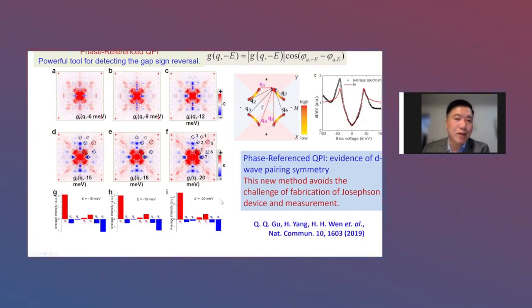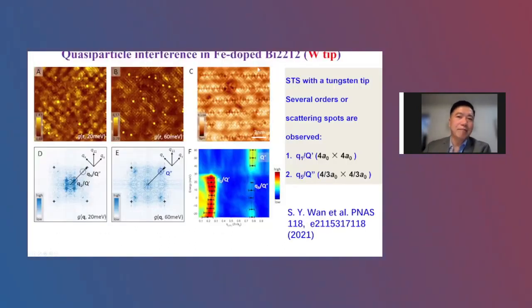Okay, so this is another story. Let me come back to the iron doped BSCCO 2212. So you can see that this is using tungsten tip measured density of states mapping. You can see this kind of block again. And when we do the Fourier transform, we see two sets of spots. One is 4a by 4a. Another one is at 4/3 a0 by 4/3 a0, again, even for this sample, okay? These are two typical scattering spots.